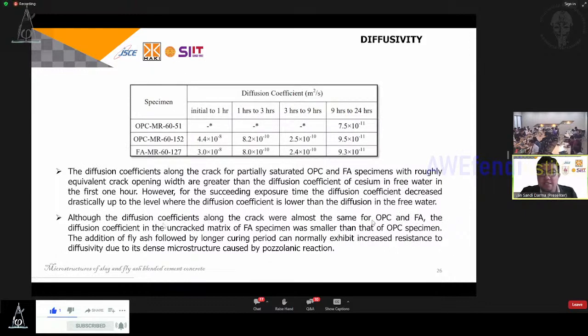And for the next, we also calculate the diffusivity along the crack. As you can see here, for OPC and fly ash specimen, the resulting diffusion coefficients are almost similar. So we can conclude the diffusion coefficient along the crack for every specimen is almost the same. It depends on the liquid itself. So here the diffusion coefficient along the crack is independent of the specimen, independent of whether you use fly ash, slag, or only OPC.